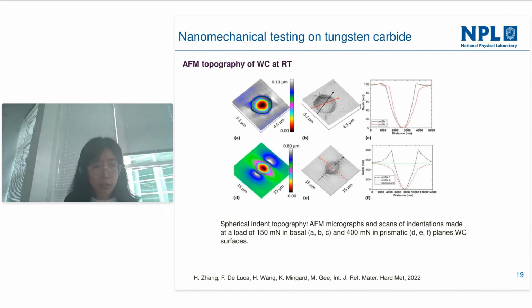And figures D and E show a twofold symmetry in the slip traces produced on the prismatic plane, along with the formation of pile-ups where upwards gliding of the dislocations occurred. Along the direction of the slip plane and across the indent, sink-in was observed on the edge of the indent. As you can see in the AFM profile in figure F, both pile-up and sink-in occur on the prismatic plane. This could be due to the slip magnitude for materials that exhibit high hardness but with soft slip systems: tensile stress develops when the slip is restricted, leading to the sink-in region.